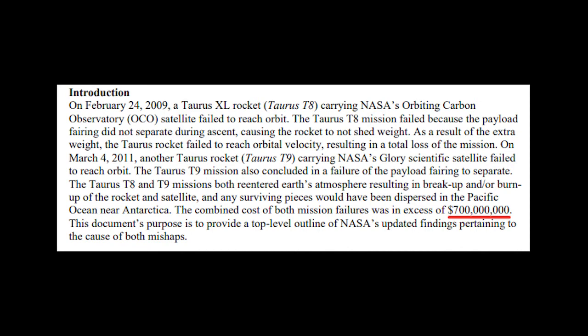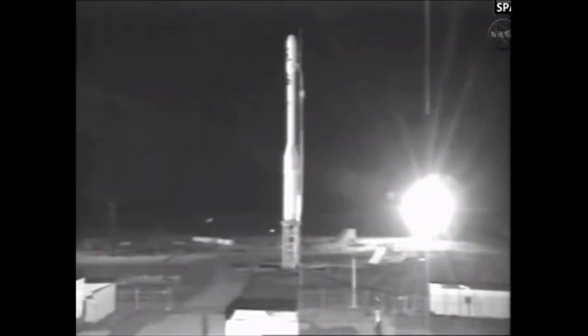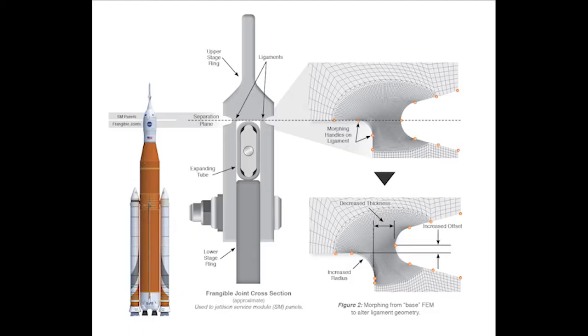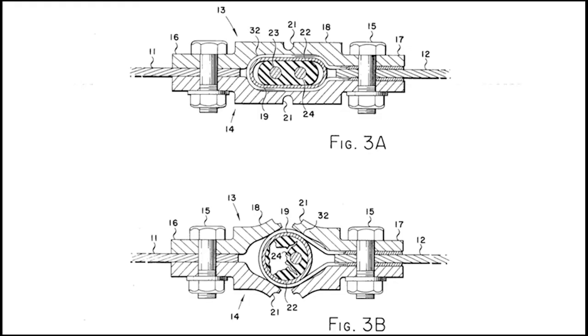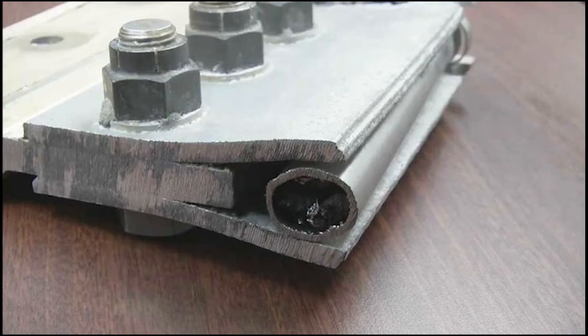Well, as stated at the end of the video, the failure was suspected to be caused by a fairing not fully separating. The T8 and T9 rockets, the two failures in question, both used frangible joints to separate the payload from the rocket. Frangible joints are three plates joined by bolts. In the middle of the joint, the inner plate is cut off and the two outside plates wrap around a large cavity. In this cavity, there is a material with an explosive on the inside. The material is designed to expand when the explosive goes off, fracturing the narrow points on the two plates surrounding the cavity and causing stages of the rocket to separate.